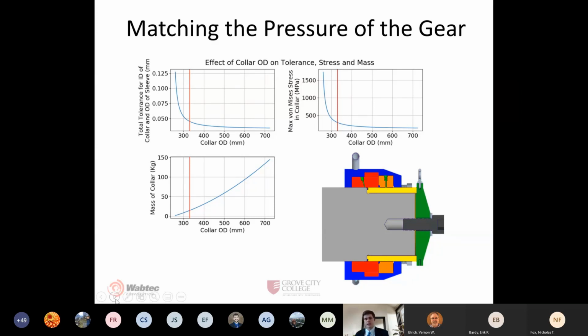What you'll notice here is that there's really not very much geometric variability built into this design. So the main thing here was the outside diameter of the orange collar there. So the collar and the sleeve are press fit, and they're designed so that the pressure of the press fit with the gear and the collar matches the press fit with the collar and the sleeve. So you have the gear and the crankshaft and the collar and the sleeve with the same pressure so that they can float off simultaneously while attached to the same pump.